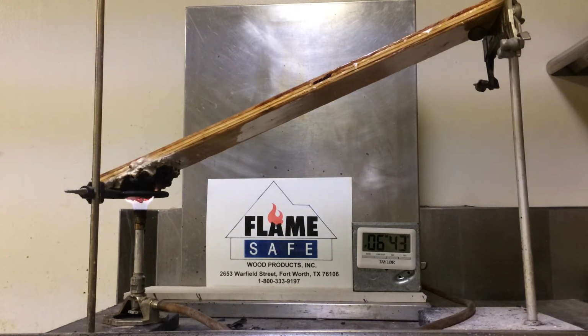During this test, you will see the height of the intumescence if you can possibly zoom in to the flame at the top of the burner and the relation to that flame to the expansion that has created on the intumescent coating. At this point, there is less than 1/2 inch distance between the flame and at the top of the burner to the bottom of the coating. That shows an expansion rate of approximately 1.5 inches or 1,500 mils.